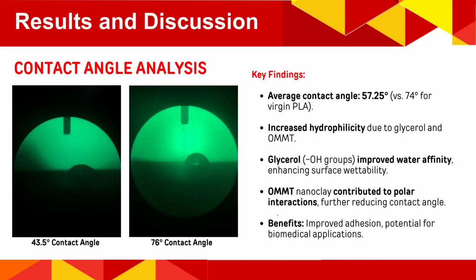We also evaluated the wettability of our material through contact angle analysis. Our formulation exhibited an average contact angle of 57.25 degrees, significantly lower than that of virgin PLA, which is 74 degrees. This shift towards hydrophilicity is due to the presence of glycerol and nanoclay, which improves the surface interactions. Enhanced wettability is beneficial for biomedical applications, as it improves adhesion and comfort.